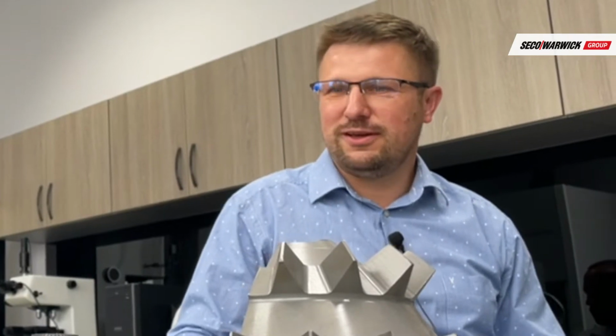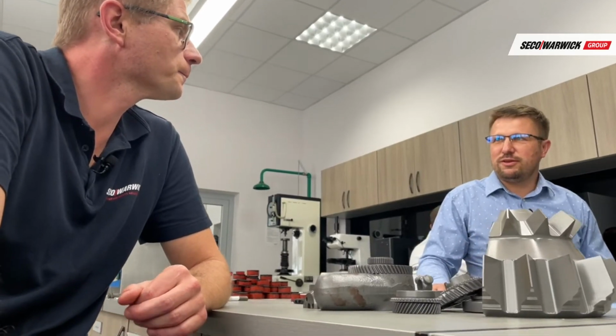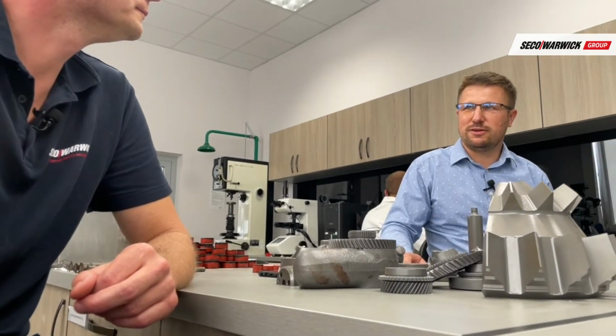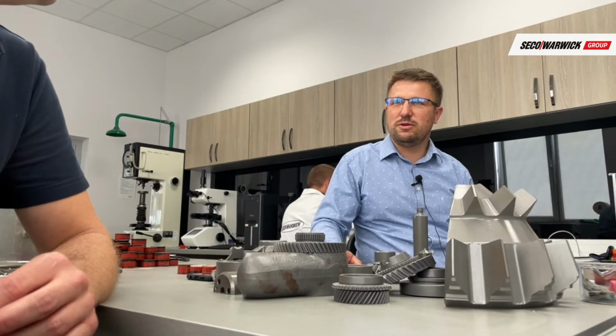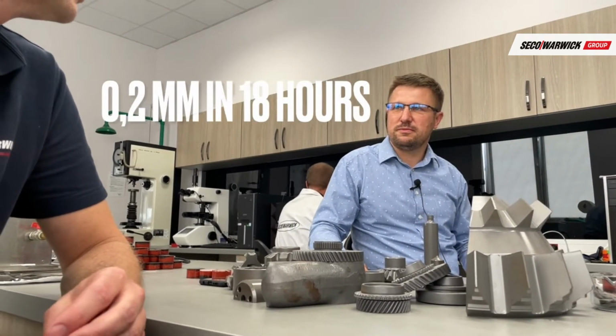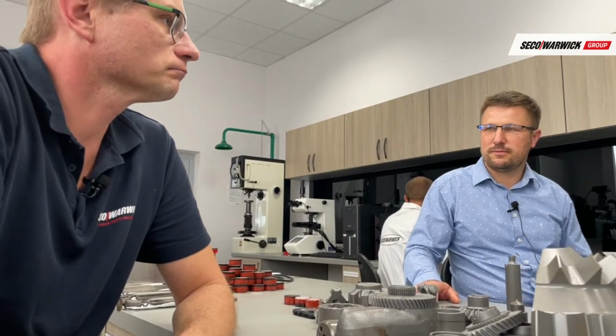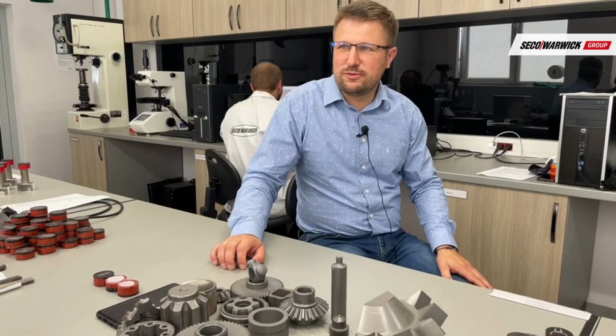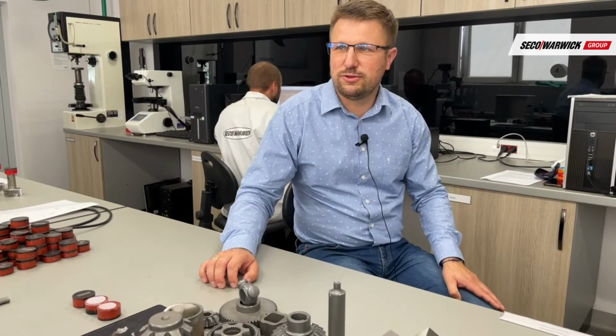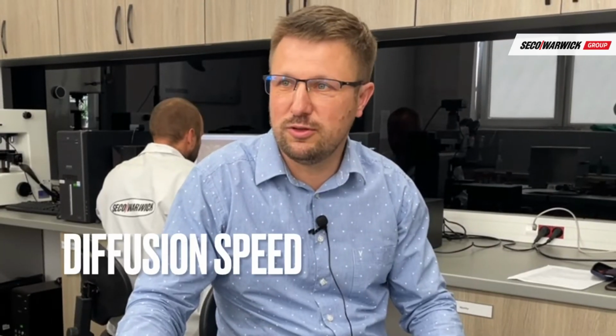Well, that's a good question. I heard it many times from my partners: in nitriding, when we would like to achieve a case depth of around 0.2, it will take more or less 18 hours. Oh, it's really a long time. When we talk about 0.2 for carburizing, I think it's a maximum of 4, maybe 5 hours. So please explain why in nitriding we need such a long time. The main reason is the time of diffusion, the speed of diffusion at the particular temperature.